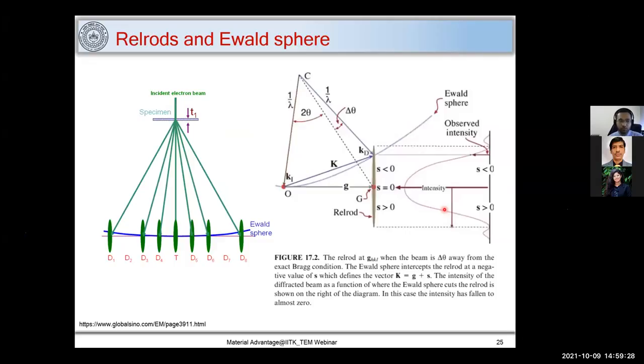Now let me introduce one important term here, which is reciprocal lattice rods. So we saw in the earlier slide those were points, but most of the samples are thin, in case of TEM, those samples are really thin. So these are not points. These will be rods. So here you can see there is a construction of the Ewald sphere, and these are rel rods. So where this Ewald sphere is intersecting, those reciprocal rods will diffract, and you can see its utility as we move along.